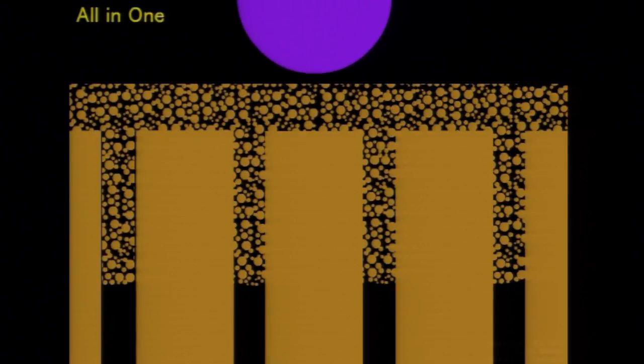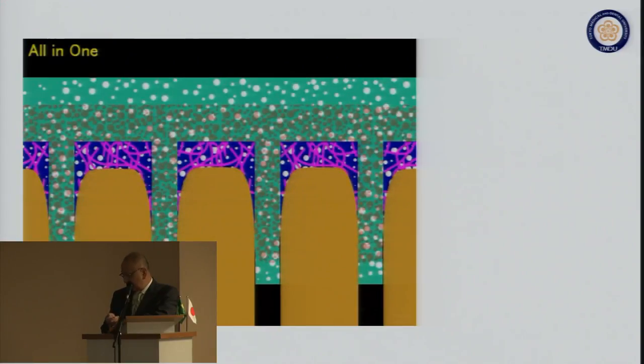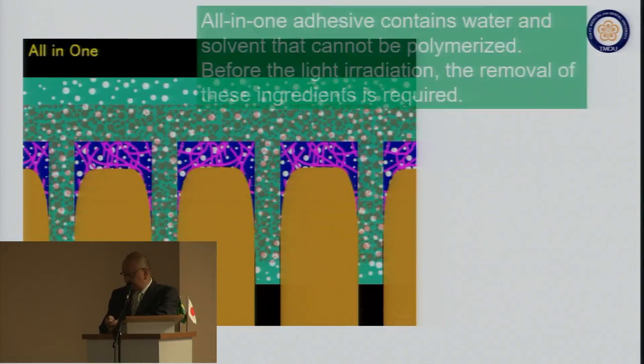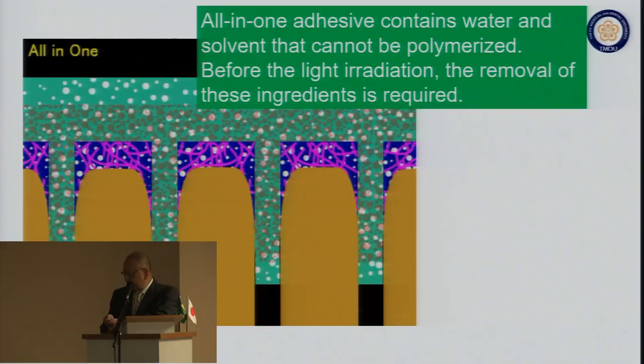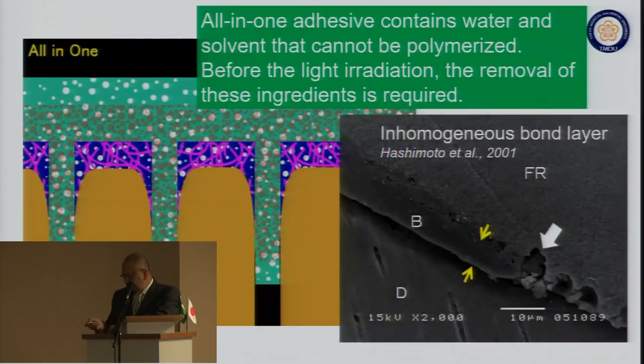This is an animation. Of course, that smear layer is mostly removed. And a very superficial layer is etched, and the bonding resin can penetrate. And we try to remove water and solvent. However, some amount of water and solvent still remain at the interface. So that's why sometimes, under the SEM observation, we observe the void at the interface between bonding resin and composite, or sometimes in the bonding layer itself.